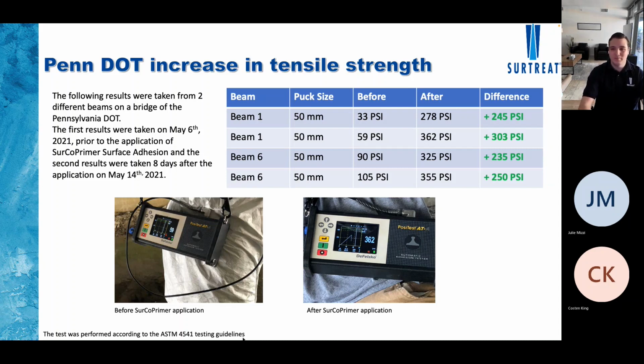The spalling due to corrosion will pop out the FRP. So we needed to treat that. There were 2 different beams. We applied our Surtreat technology, our circle primer, and after the application, we saw increases of 245, 300, 250 psi, which in fact allowed the structure to be repaired with FRP.